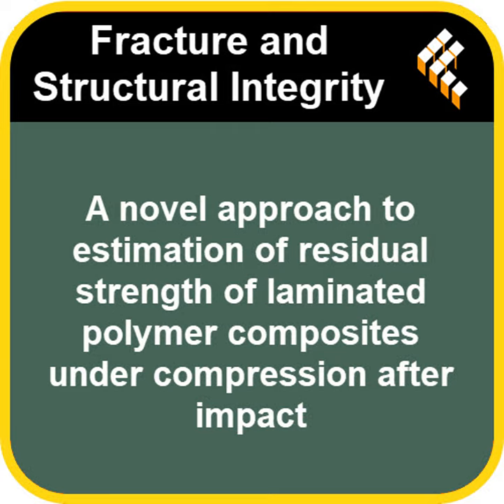Wow, what an exploration into the hidden world of material science. We've really seen how even these low-velocity impacts, the kinds that might leave no visible trace at all, can drastically reduce the strength of these critical polymer composites. We learned about the multi-stage nature of the damage, that fascinating anisotropy, how different fiber setups respond differently, and that crucial link between internal delamination area and the actual remaining strength. That connection really seems like a potential game changer for testing, right?